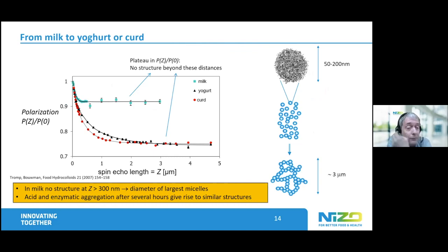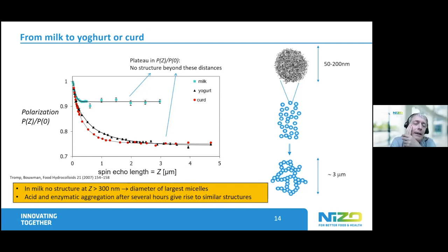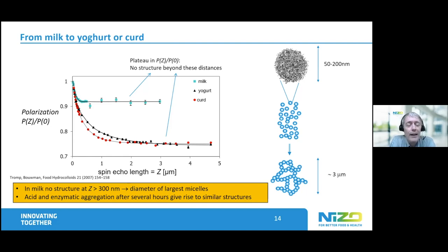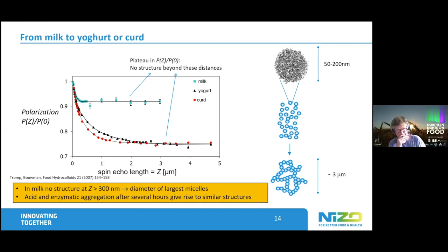The only thing I can add is that there is a subtle difference between structure formation after cutting the hairs versus after collapsing the hairs — so making rennet is not precisely the same as making yogurt. It probably has something to do with the fact that when you cleave with an enzyme, the casein micelles are locally cleaved; it is not a homogeneous cleaving. So you get patches where the casein micelles start to stick together, whereas acidification is a more global effect.